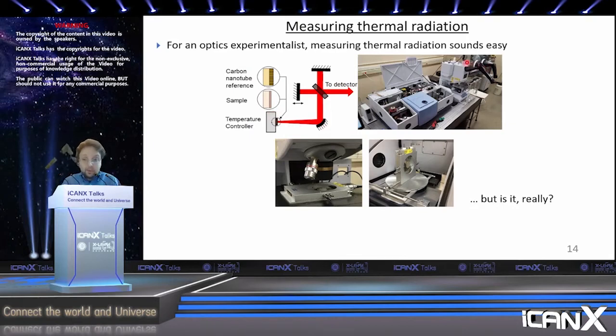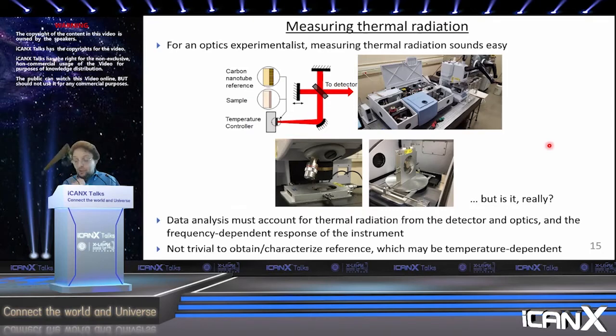And so in our lab, we have this Fourier transform infrared spectrometer connected to an optical microscope, which means we can look at very small samples and we can measure thermal radiation from small samples. We have a stage that goes up to very high temperatures and also very low temperatures, and that's very useful. We can change the angle of the sample, so we can look at angle dependent thermal radiation, and life should be really good. It turns out that it's not actually that simple. When I joined UW-Madison and started getting these experiments set up, it took us something like a year and a half or 2 years to be able to get good, easily understandable thermal radiation measurements.